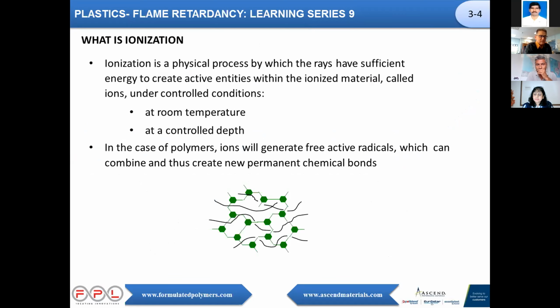So what is irradiation? What is ionization? I will not go too much into details, but basically you are bombarding your part with a very high energy. And this high energy interferes with the polymer chains. This takes place at room temperature, so it's not a very harmful treatment for the product. And what happens is that, of course, this energy breaks the chain. And there is a competition between breaking the chain and creating a network.